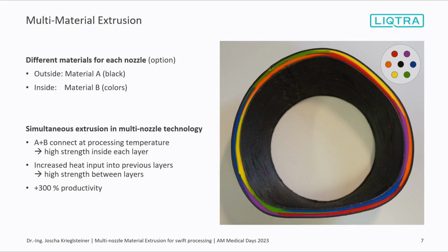Then you have more material being deposited in a limited time frame, limited area, limited surface, and that gives you more heat introduction into the part, into what you printed before, the lower layers, and that makes them heat up to a higher temperature. This way they are also more active, with a higher tendency to bond. And what we found, we had specimens measured for PLA, we found an increase in build-up direction of 37%.